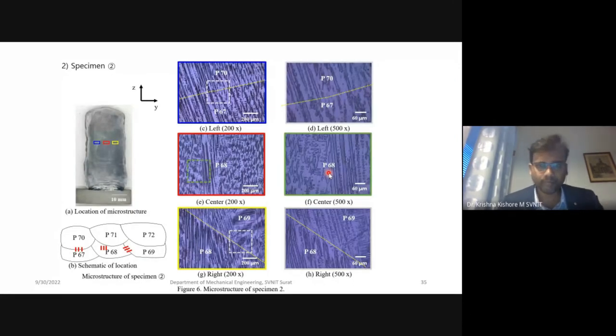If you see in the next figure, we have taken different layers. This is the case of parallel deposition in specimen number two. If you see, the layers are continuously deposited, and we have assigned numbers for each layer. Let's say 67, 68, 69, 70, 71, 72. We have deposited like this. So first layer will be deposited, second layer, third layer, and on top of the first layer, again the fourth layer will be deposited like that. So in the parallel deposition case, the heat will be conducted from P70 to 67. After deposition of this layer, the next layer will be deposited subsequently at a later stage, right? So once 67 has been deposited and we are depositing 68, the 68 layer will conduct heat to 67, and it will also absorb heat from the 71 layer, like that.